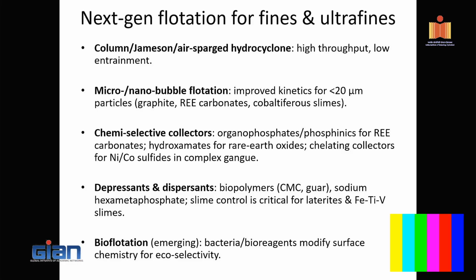Now, for such a fine particle, a big bubble is not able to make enough contact, so you create finely dispersed bubbles. That's what fine flotation is: you target the finer size particle, but ensure your bubble is also fine enough to have an effective streamline. For example, if the 10 micron particle is moving along with water, and you create a bubble of a millimeter or less, it might also go in a similar manner. Then both will be on a similar path of the flow circulation, and there is a probability that you can enhance the flotation. And that's from a hydrodynamic point of view. But of course, chemically you can also enhance it by adopting certain reagents, which can minimize the disintegration of the bubbles to give stability to the flow and bubbles. So that's where we look at it.